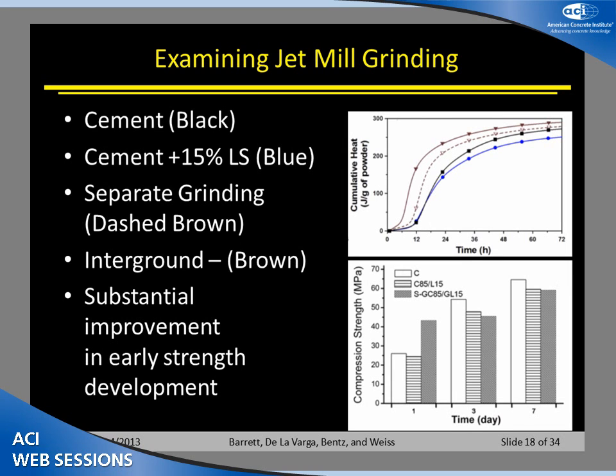To showcase that a little bit, what I've shown here is the cumulative heat that's released in those materials. This is a measurement of isothermal calorimetry, so it's essentially a rate of reaction. Here we can see the black line is the conventional cement system, and cement plus 15% limestone is shown in blue. If we do separate grinding of those materials, we essentially can accelerate the reaction and get more reaction happening. But if we intergrind the materials, again, even faster and higher heats of hydration are going on in those materials.